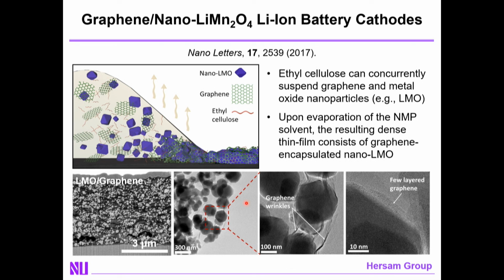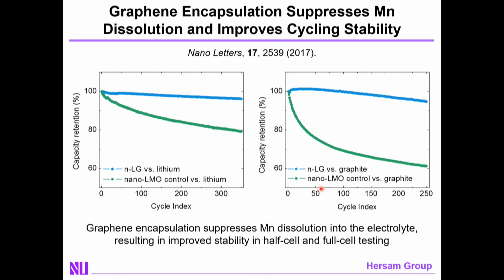OK, so how do we do it? Well, what we're going to do is take our cathode particles, in this case lithium manganese oxide. We're going to put them into solution with solution-processed graphene. We process this with a polymer called ethyl cellulose, forming a stable dispersion. We then cast that onto a substrate. And if we have enough graphene present, we're going to find that the graphene will form a coating on top of the cathode particles that make up your composite electrode, giving you a conformal few-layered graphene coating. This will serve as the artificial SEI layer.